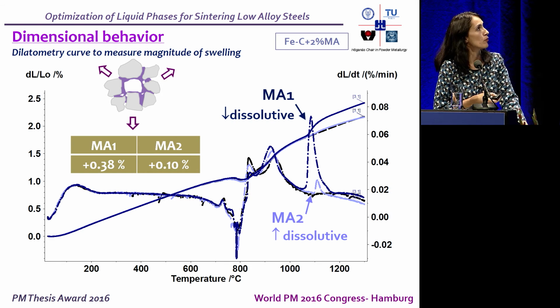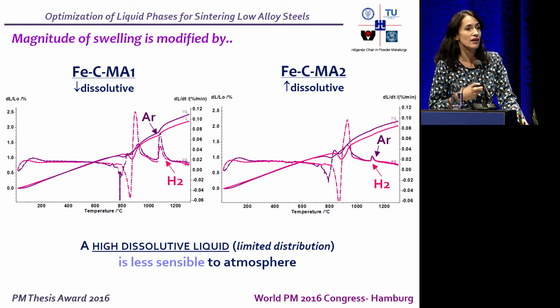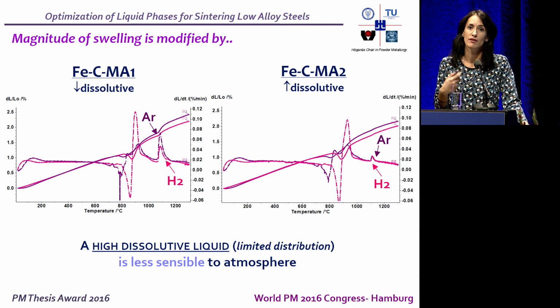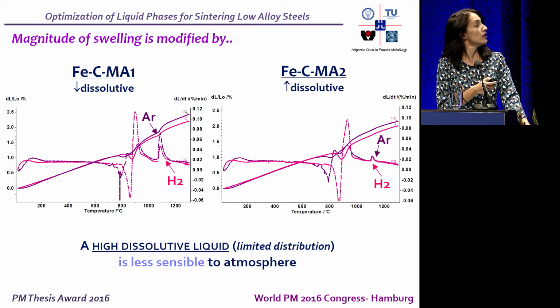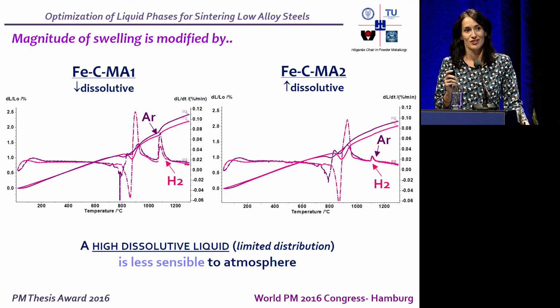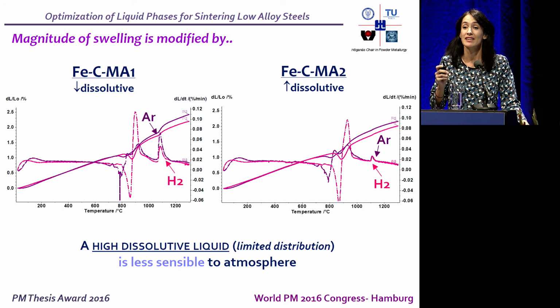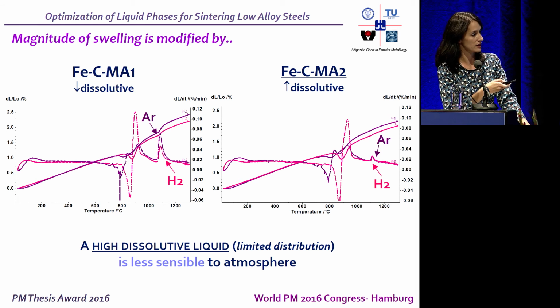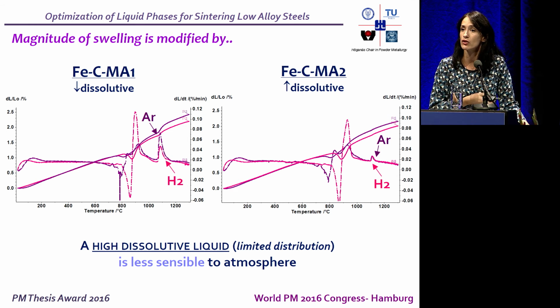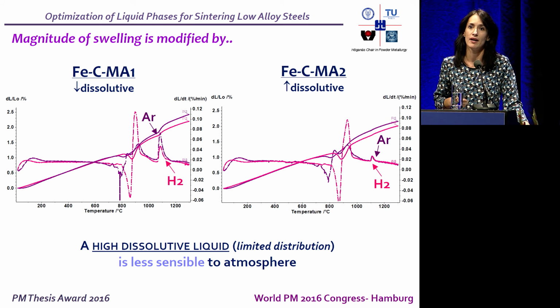More interestingly, we can design liquid phases with different sensitivity to the solid that they are wetting. Here, and this will, of course, directly affect the dimensional behavior of our steels. Here, what we can see is that if we have a low dissolutive liquid phase, only under reducing conditions, we can decrease the amount of swelling that we have.